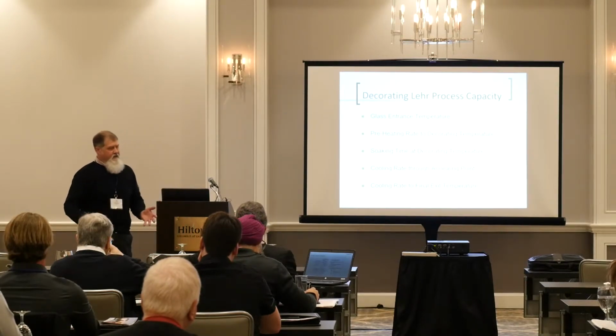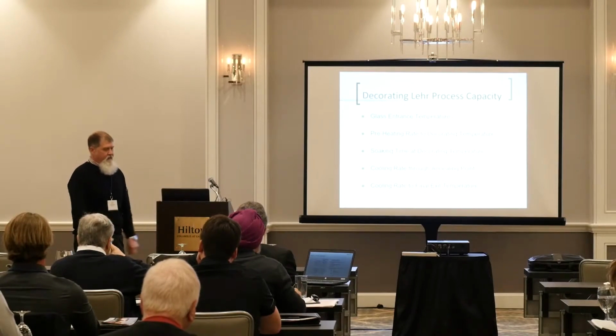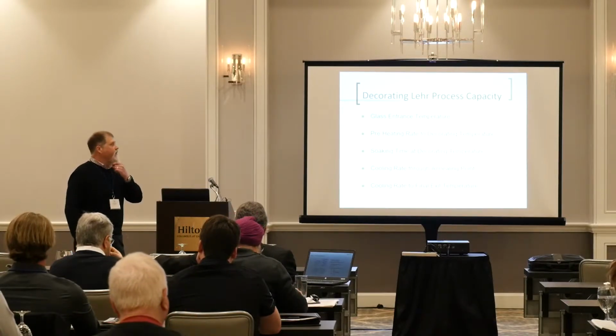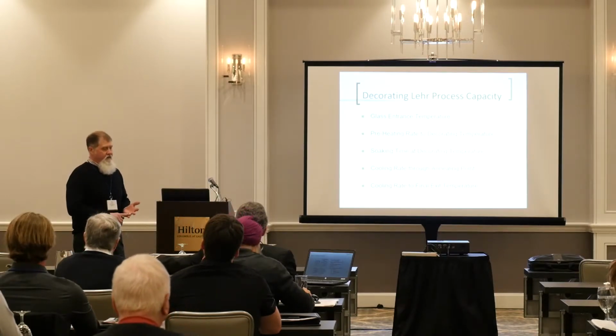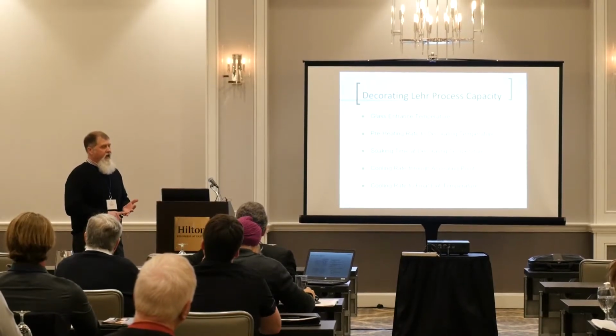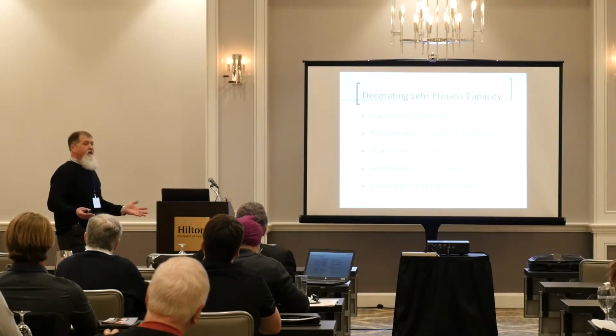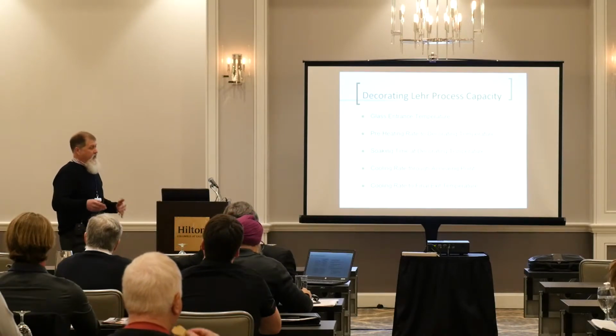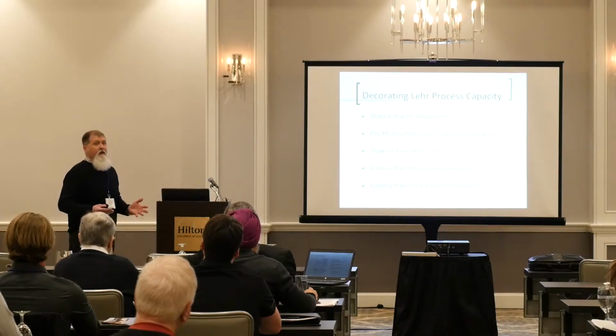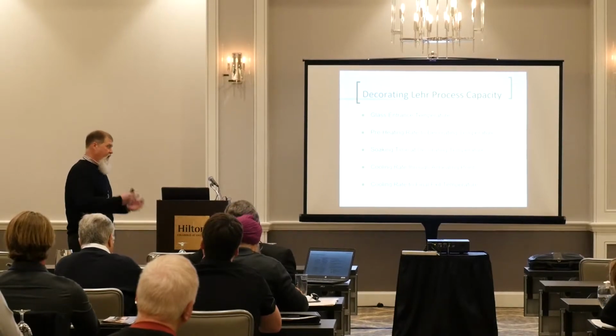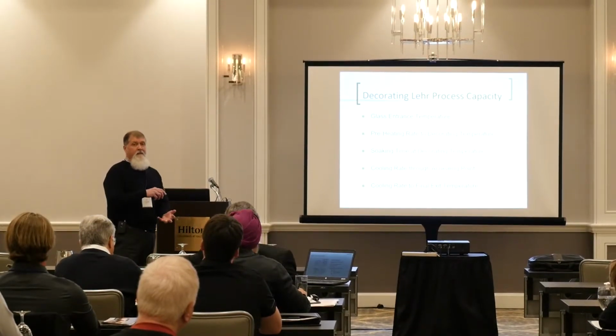I've done a few of these at SGCD, and I do annealing seminars throughout the year. So if anybody's ever sat through one of these with me, specifically with the decorating folks, you've got to remember that if you're firing the glass up above the strain point, which is going to be the case anytime you're firing a ceramic decoration, you're firing it up above about 950 degrees or so. Okay, you are now determining the final grade of annealing on that glass. Not just the decorating quality, but the physical property of the glass as far as the annealing strength is concerned.